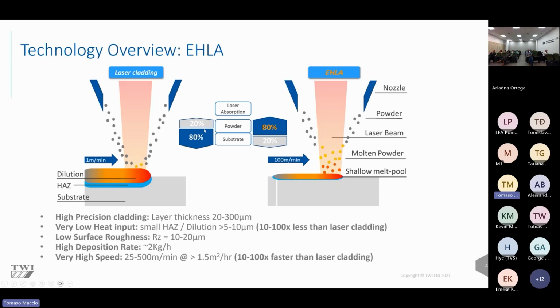You can see from where my cursor is here, there's around an 80-20 dilution to substrate. So you're getting a lot of mixing, and this happens because the focus of the laser beam is melting on the substrate with the powder, whereas in EHLA, the melting happens around 1 to 2 millimeters above the substrate. So in this process, the melting of the powder happens above the substrate and is sprayed on. While it's still molten, it is sprayed onto the substrate and sticks to the substrate, creating a metallurgical bond.